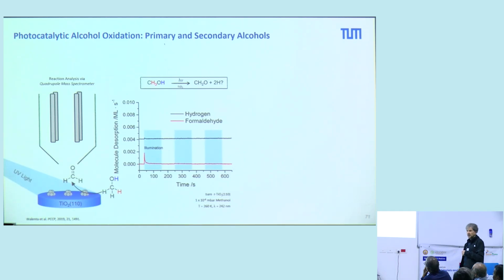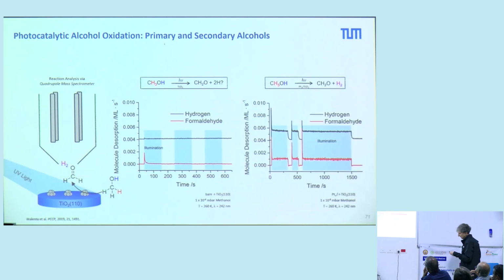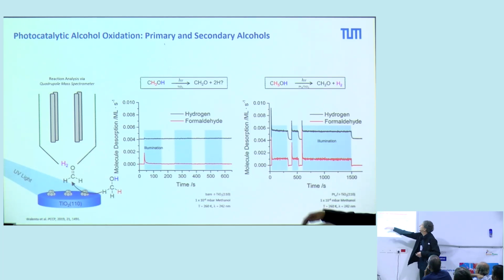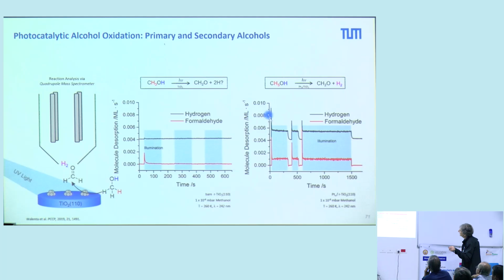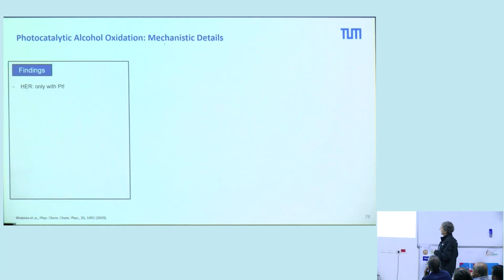Now we can put clusters, co-catalysts on the surface, and the picture completely changes. You see now steady formation of formaldehyde as long as we shine light on the photocatalyst, and we also see hydrogen that is produced. You turn off the light, you see an immediate decrease of the formaldehyde, and we have a thermal tail of the hydrogen. That means we need platinum. This is what we learned. We need platinum in order to produce hydrogen.